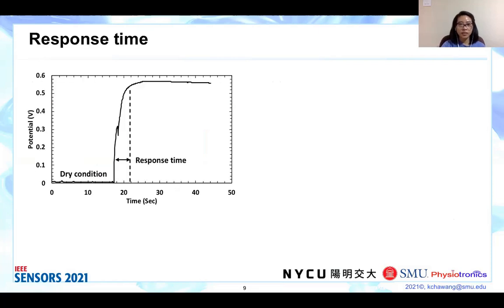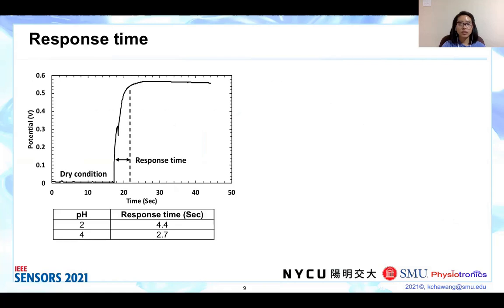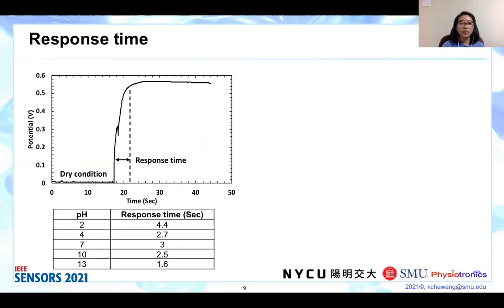To study the response time, we perform 2 types of tests. First is when the electrode is immersed in buffer from its dry condition. The response time at pH 2 is 4.4 seconds, at pH 4 is 2.7 seconds, at pH 7 is 3 seconds, at pH 10 is 2.5 seconds, and at pH 13 is 1.6 seconds.